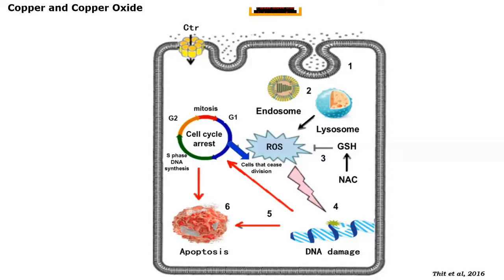However, very unfortunately, it is not very favorable from the toxicity assay point of view, because copper ions are capable of inducing oxidative stress. They are very famous for creating these ROS dependent effects when they are taken up. What this model is showing is they are mostly taken up by endocytosis. Then they go to the lysosomes and via autophagy there is ROS generation, and then there are other molecules that get mitigated by the antioxidants, and several other downstream things taking place, finally ending with the possibility of DNA damage and cell death by apoptosis.